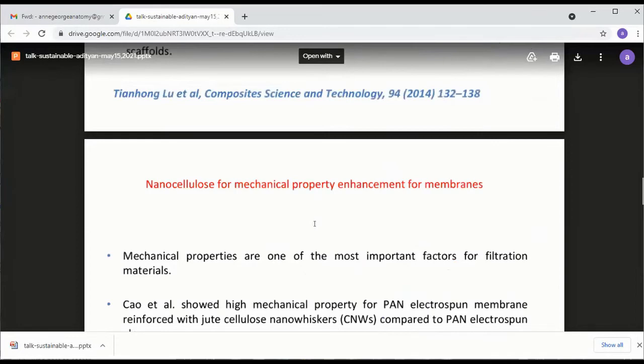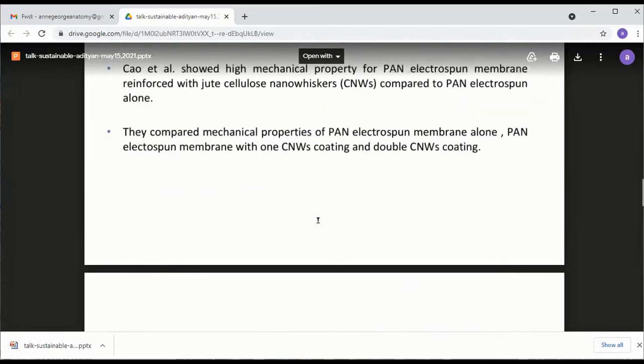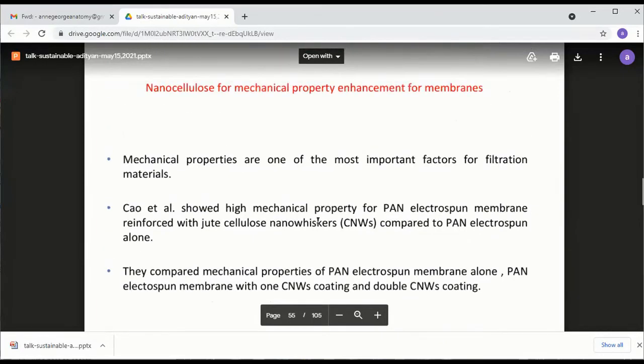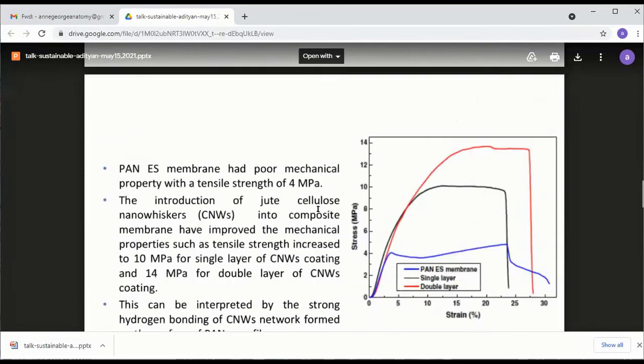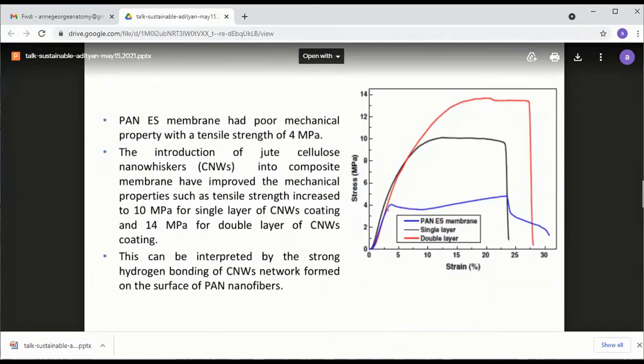Nanocellulose could be a good material for reinforcing commercial membranes. You see, commercial membranes are usually made of electrospinning technique. And if you look at commercial membrane, look at this membrane. This is made from polyacrylonitrile, the blue one. Look at the modulus, look at the mechanics, poor. But if you give a coating on the surface using nanocellulose, one side coating, you see the strength goes up. Two side coating, still the strength is further increased. So dear friends, the commercial membranes could be reinforced by coating with nanocellulose.